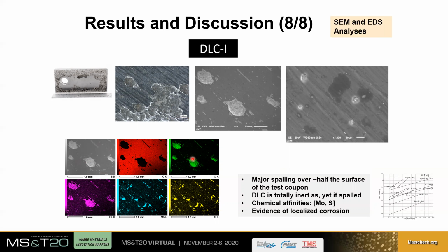Okay? So the DLC has spalled quite a bit. There is a bit of evidence of localized corrosion through perhaps pitting. But other than that, it's important to see that there is no chemical affinity between the DLC and the rest. However, this coating is performing worse. So a strong affinity towards sulfur or H2S for a coating is not synonymous of very poor corrosion resistance.